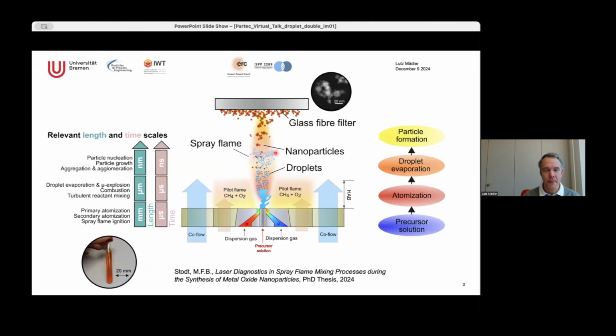And then you have a co-flow. And while these droplets are evaporating, you set free some of the metals you have dissolved in that solution here. And while you set them free, you have them in the gas phase as individual molecules in the best case. And then these individual molecules, they nucleate and create your new materials. And then they coagulate to form bigger particles, they sinter. And at some point, you can quench this flame, basically because the fuel is being burned out. And you have a lot of gas entrainment in this gas flow. And then you cool this process down very quickly.